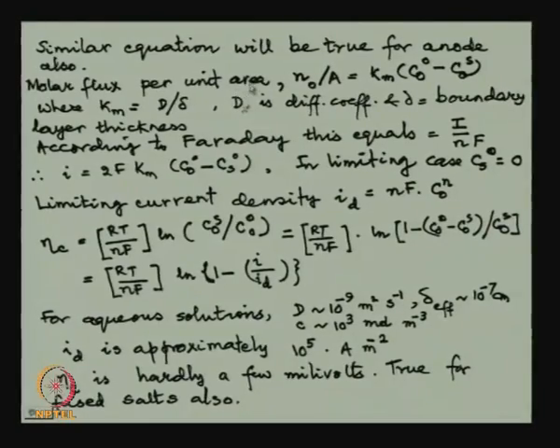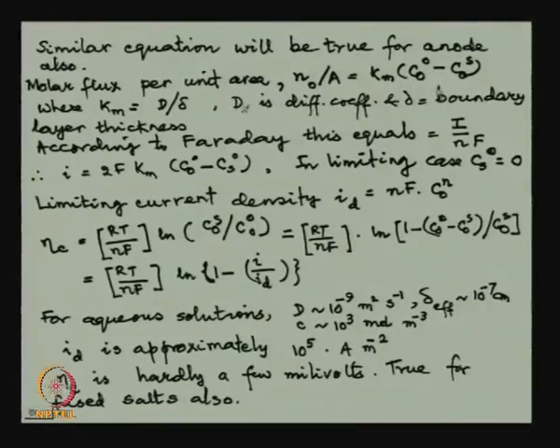Now, molar flux per unit area is total flux divided by A, which is a constant, into C naught minus C s, where C naught is the bulk concentration and C s is surface concentration, K m is the diffusion coefficient term, where K m is D by delta, D is the diffusion coefficient and delta is the boundary layer thickness. You are aware of the diffusion equations. According to Faraday, this equals total current divided by valence into Faraday constant F. Therefore, for I, the current per unit area, we can get an expression. In a limiting case, where the surface concentration falls to 0, the limiting current density I d is given by this expression: valency, Faraday constant, and concentration in the bulk.